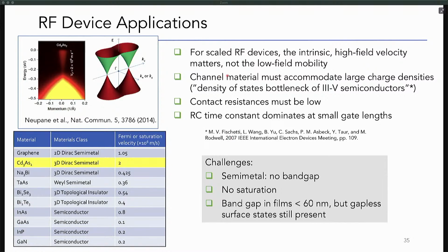The other important thing, if you think about transistor applications, is how much charge you can accommodate. So speed is important, but so is how much charge you can accommodate. For example, III-V semiconductors, which have very low masses, have trouble accommodating a lot of charge because they have a single minimum in the conduction band. There are also other important practical considerations: contact resistances must be low, and RC time constants become important with small transistor gate lengths. The challenge with cadmium arsenide, of course, is that it's not a semiconductor, it's a semimetal, so there's no band gap. Applications that require a completely off state will, of course, be difficult.